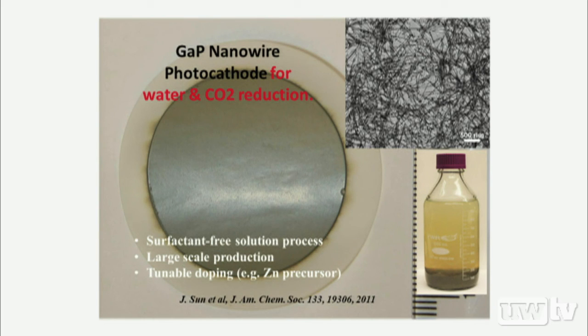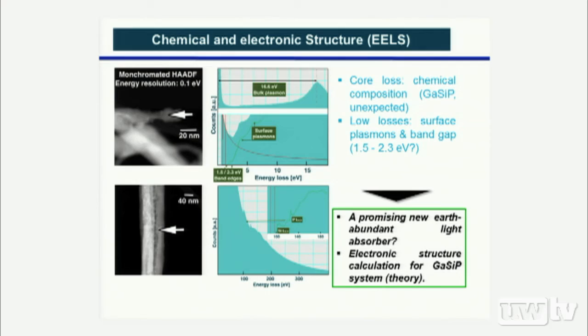Very quickly, I will show you two examples of new semiconductor materials we're developing. One is a low temperature chemistry we're developing for gallium phosphide, where we utilize a similar chemistry, but this time mixing in a silicon precursor to make an alloy compound, a gallium phosphide silicon alloy, with a tunable bandgap. This is a new composition, and the bandgap can now be tuned back to 2 eV. This is a photoelectrode material with a new composition, and it's metastable. It does not exist in thin film form.